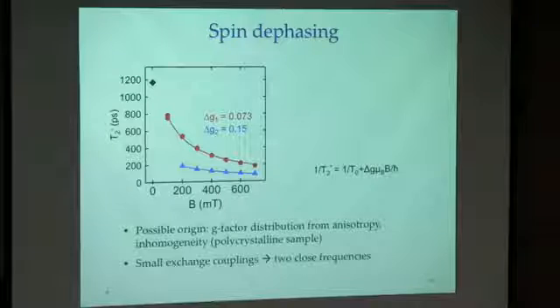As we increase the magnetic field, you probably also notice that the lifetime gets shorter. So we plot the lifetime as a function of magnetic field. It decreases very fast, and we thought it's dominated by spin dephasing. Initially, we oriented those spins all in one direction, but they precess at slightly different speeds because of the g factor distribution. As they precess even more, the distribution gets larger and larger. Eventually, if it's more than 180 degrees, they cancel each other. So that's why you get a decrease of the signal.